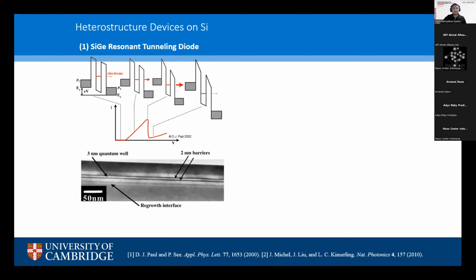Okay, so besides laser, what set of devices do we need for this silicon photonics application? One answer is silicon germanium system for resonant tunneling diode, or RTD, to realize an oscillator. In RTD, we are interested in this negative differential resistance, or NDR, region here in the IV characteristic. This characteristic can be realized using this kind of band structure. Classically speaking, when an incident carrier approaches these double barrier structures with energy the same as the energy level inside this quantum well, it will be able to tunnel with tunneling probability equal to one, or unity. This manifests as the peak in the IV characteristic. So that's why you could get this kind of negative differential resistance region.